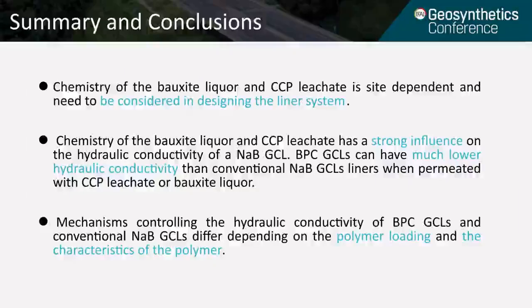Here comes to the final of this presentation. So we want to summarize what we learned and make conclusions. So first conclusion is that the chemistry of the bauxite liquor and the CCP leachate is widely site dependent and needs to be considered in designing the liner system. Especially we find out the bauxite liquor is very highly alkaline, and also some of them may have high ionic strengths.